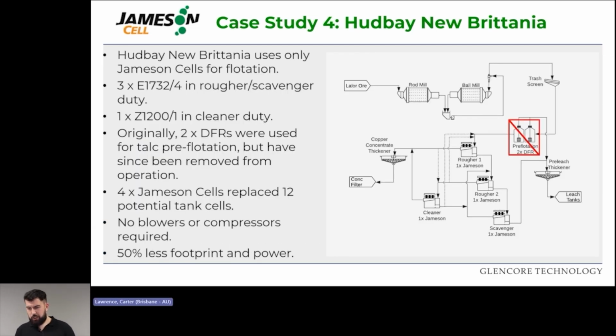So you can see the flow sheet on the right here. All of the flotation is occurring only through Jameson cells. There were originally 2 DFRs there for like a pre-flotation. Those have since been removed from operation, so it is only Jameson cells. Now, 4 Jameson cells replaced a potential 12 tank cells. And that cut the footprint by about 50%, as well as the power by about 50%, because you don't have any agitation requirements. And there's also no blowers or compressors required.